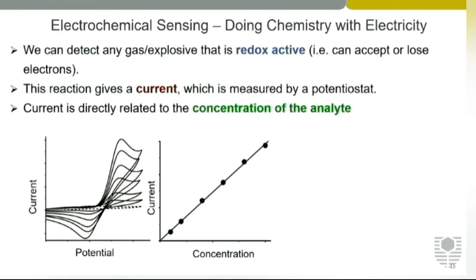So how do we actually measure our response for the sensor? This is the analytical part of it. We can detect any gas that's redox active, so it either gains or loses an electron. And when this happens, we see a current which we measure with our machine called a potentiostat. In this case, you can see this is an oxidation process of a gas at different concentrations. And if you plot the peak current here, the peak current will be directly proportional to the concentration of the gas. So once you've calibrated your sensor, you can then take it into a real environment. You'll measure a particular current, and then you can relate that to the concentration.